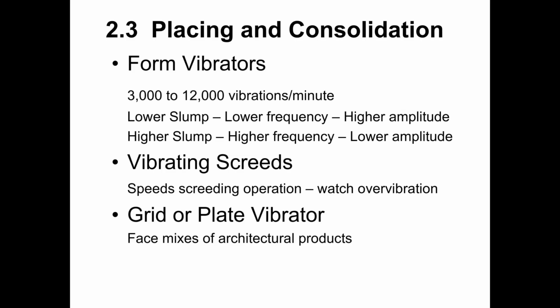So the advantage to using a grid or a plate vibrator is you get very uniform vibration throughout the full surface of the panel. The downside is that it is time consuming. It takes a while to set that plate or grid vibrator down, let it vibrate for a few seconds, pick it up, set it down again, and keep moving it until you've got that whole panel surface covered. So it's very effective. You get very nice looking architectural finishes, very uniform distribution of your aggregate within the face mix, but it is time consuming.